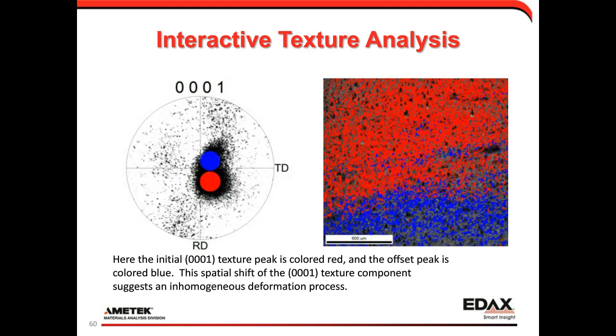Now what I've done is I've selected a single color for both, and I've clicked on a point to show a red distribution and then a blue distribution. So we see a strong texture that's developed, and then it's shifted into a little bit different area in terms of this part of the wrought alloy component. And so clearly we have an inhomogeneous microstructural distribution that we've identified by analyzing the asymmetry of that pole figure.